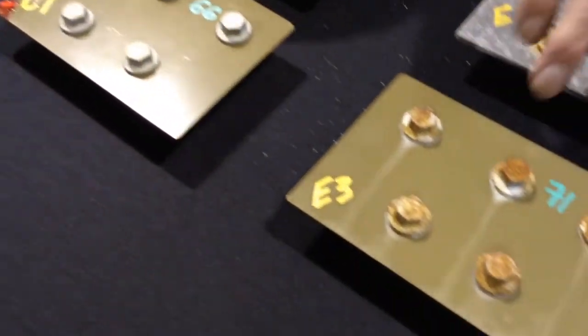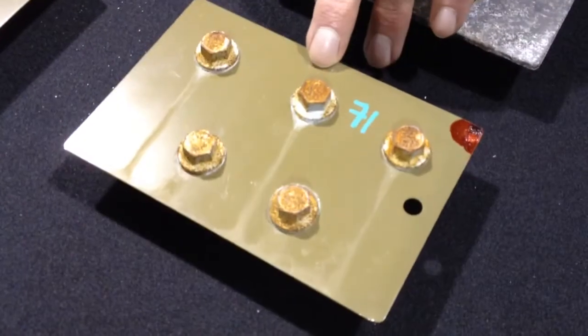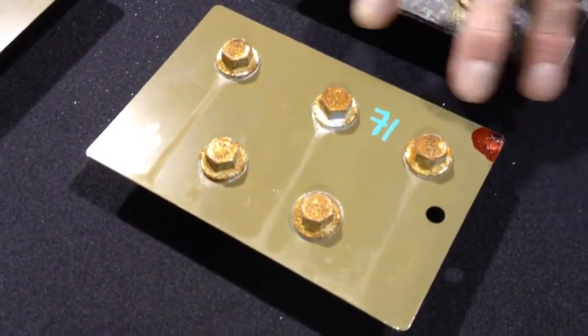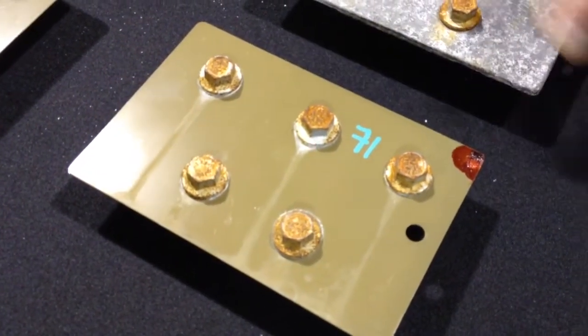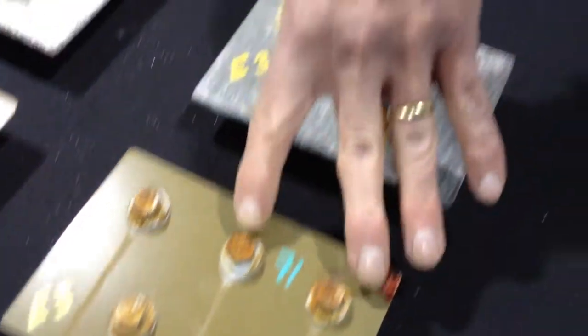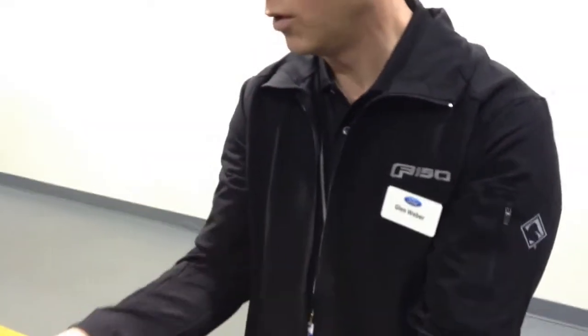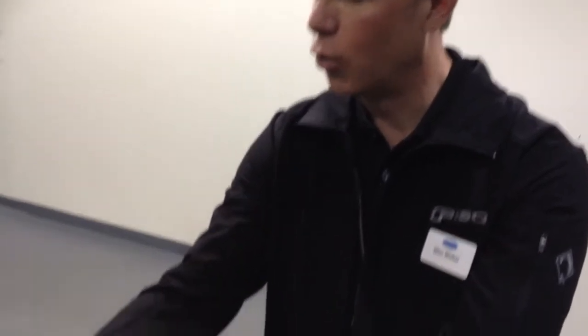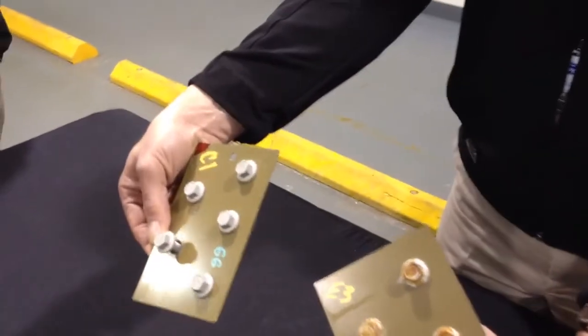And again, the same thing. Completed the test in less than halfway. So not only do those fasteners look terrible, we know from this test that the coating itself was not very robust. But now the fact that when you torque down a fastener, if you look closely, you can see a ring under the head of the fastener in both cases.